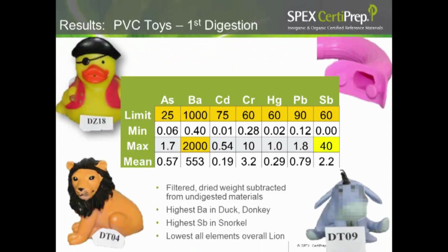We did try to find some paint samples, and it's very difficult to sometimes isolate just the paint sample from the polymer underneath. In many cases, these toys had been used for another study earlier, and by the time the metal study came around, there might not have been a lot of paint in some of the areas of the toy to isolate a large enough sample to give us an analytical result.